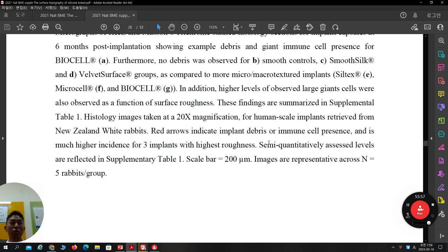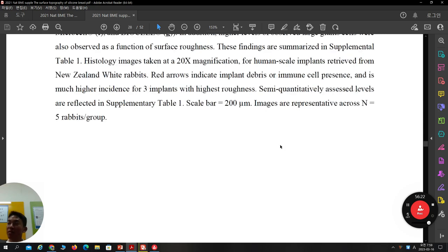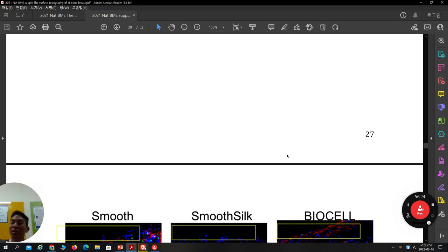So for supporting that notion, what kind of experiment can you do? You can do H&E, and you can do subcutaneous study, like 3 weeks or 1 month, 2 months, and then check, is there any inflammatory signal ongoing or does it decrease, and is there any debris around there? And then we can easily find out that they're okay. This is the reason why we can do many subcutaneous studies to check the tissue stability.